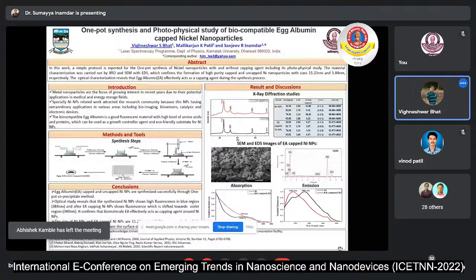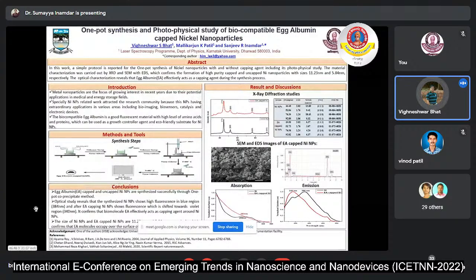airtight vessel. In order to confirm the formation of nanoparticles, I used material characterization. Those are X-ray diffraction studies and SEM EDS studies. From X-ray diffraction, it is confirmed that the structure and composition of the synthesized nanoparticles is in nickel form.